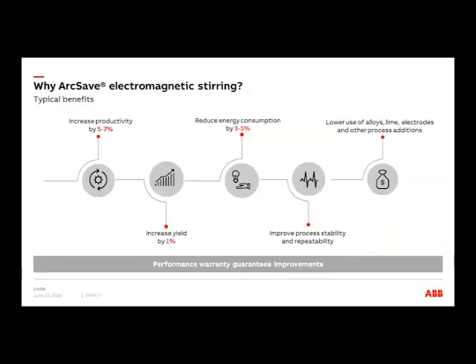So, what are the typical benefits that we can get out from the ArcSave? We have seen 3 cases, SDI, Avesta Outokumpu, and CEA in South Korea. Of course, we can increase productivity by 5 to 7%. We can increase the yield of the steel by 1%. We can reduce the energy consumption by 3 to 5%. We can improve the overall process stability and repeatability. We can have a much better endpoint prediction to the next process step. This, of course, also gives a lower use of alloys.